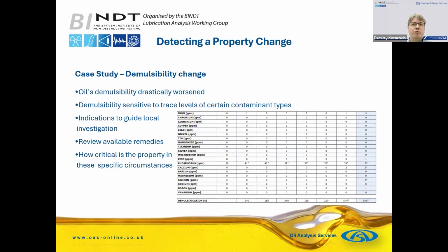Another example of detecting contamination through a property change, we had an oil sample where after a long time of good demulsibility performance, we had a sample with poor demulsibility. So instead of demulsifying after 210 seconds, after 1200 seconds, there was still only 5 milliliters of oil separated. We repeated with follow-up sampling just to check, make sure there's no issues. And the result held. And one of the things we noticed was very low levels of calcium and silicon in the system. And demulsibility of oil is a property that can be sensitive to very low concentrations of certain contaminants. So this information gives the customer a chance to investigate, find out where the contamination may be coming from.